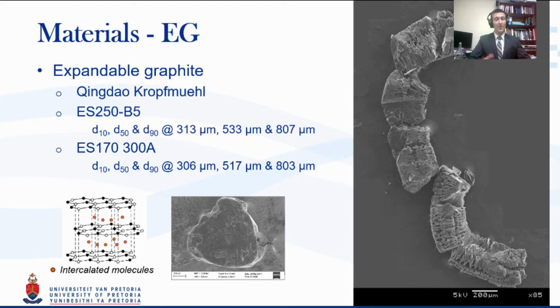And we determined that that was due to KMnO4 used as a very strong oxidant at the start of the intercalation process. So what this caused is that this material actually has a lot higher oxygen to sulfur ratio, which has some positive results in that it expands even more explosively, as I'll show you soon.